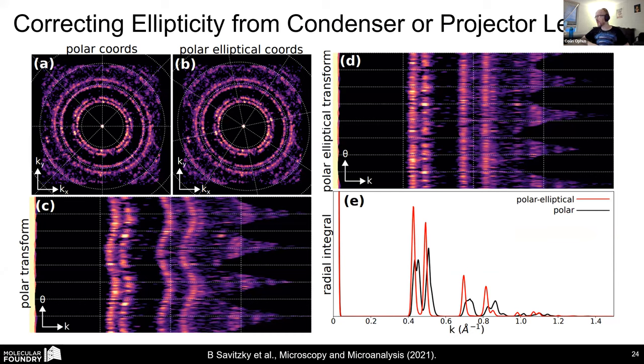And so what you're seeing on the radial integral, this is a crystal material, but you can do radial distribution function mapping for amorphous, semi-crystalline, or crystalline materials. This red curve is what you want to generate. This is the diffraction intensity as a function of the scattering vector. What you do with this pattern is you subtract out the single atom scattering form factor, which you fit, and then you're left with what's called the reduced structure factor of the material. Then you take a type 2 sine transform, and that gives you a real space image of an RDF. And so that would look something like this.